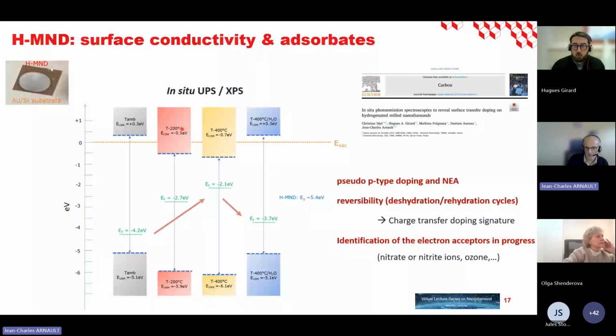So in situ, we perform two annealing steps and then measurements of the sample. And you see that we lost this negative electron affinity after the first annealing at 200 degrees C. And also, we have lost the p-type character. Then, if the sample is rehydrated and measured again, you see that the situation is very close to the initial one in terms of negative electron affinity.